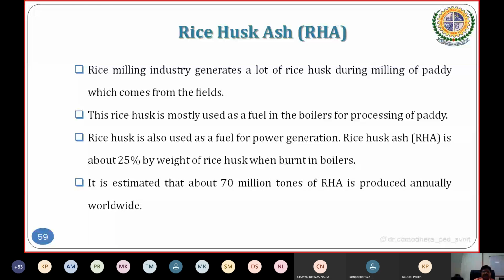The RHA in turn contains around 85 to 90% amorphous silica. For every 1000 kg of paddy milled, about 220 kg, about 22%, is husk, as rightly said earlier. And when this husk is burned in the boiler, it is reduced to about 55 kg of RHA generated. This is a simple calculation.